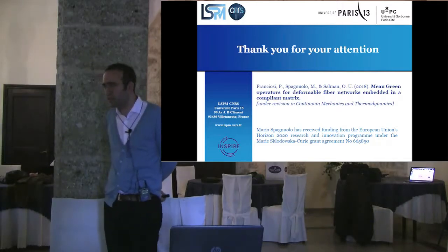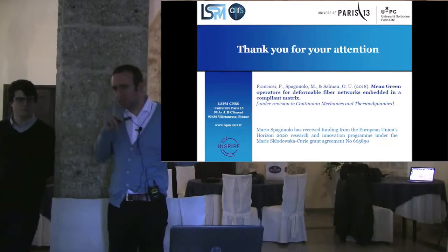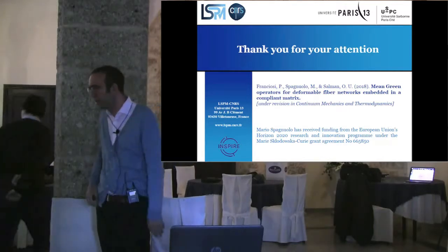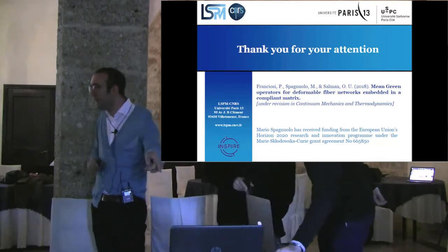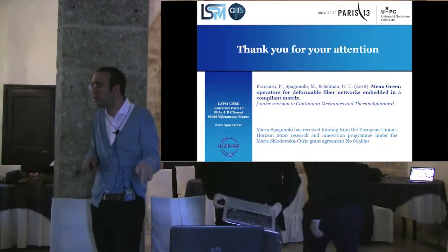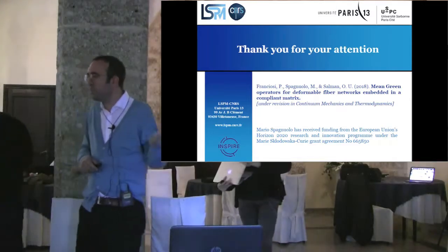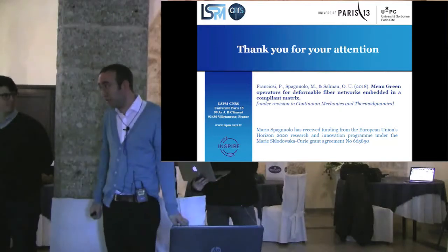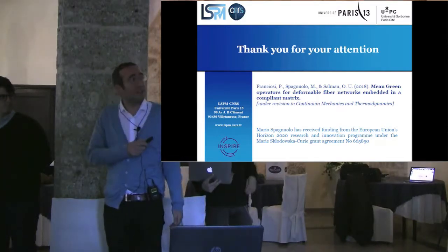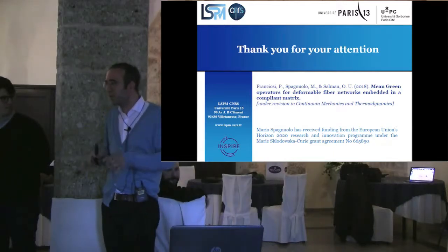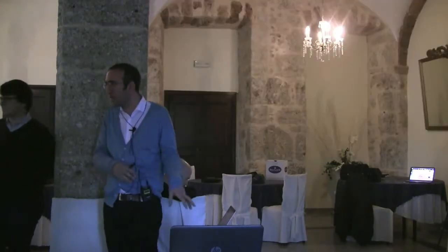Yes, I understand the physical question. I think that in the analytical calculus of Green operators, you don't consider this effect of friction between the fibers when they approach one another. In the numerical calculus, you have this because COMSOL knows this kind of thing, and in fact you cannot have the same results as the analytical ones, also because you are making some simplifications, and this is one of them. The analytical results in the case of very close fibers give some problems because of the nonsense of the problem with this kind of method.